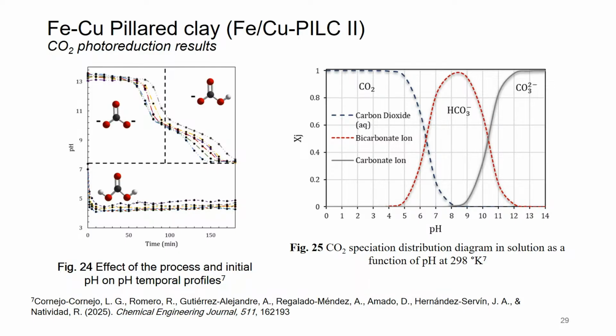Here you have the carbonate. That means at the beginning of the reaction with sodium hydroxide, you have mainly carbonates because you are working in this area here. But with water, you are working in acid pH. That means you are working here, and in acid pH, we have mainly molecular CO2. So actually in water, we are really conducting the CO2 photoreduction, while at a higher pH, we are doing the chemical reduction of the carbonates and bicarbonates.